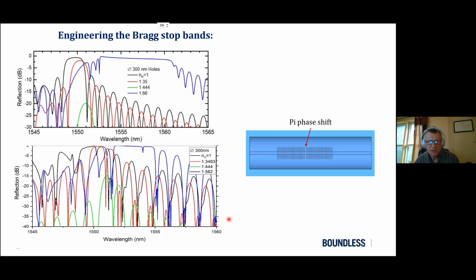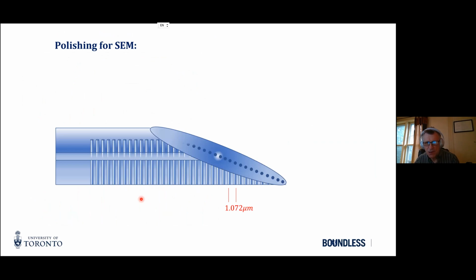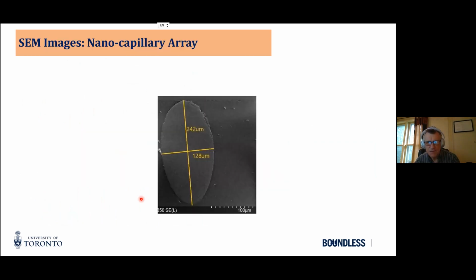So these are some simulations, say with a pi defect, you can get these notches in the stop bands. And these are different refractive indexes of the holes filled with liquids. So this all really works. You can see strong Bragg shifts. And so here's just a picture show verifying that these holes are forming.